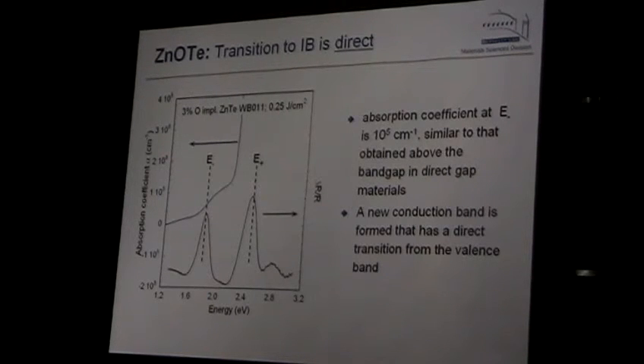So then we said, okay, now in order to make a solar cell, you need to have strong enough absorption. So we looked at the absorption coefficient of this, and in fact there is a strong absorption for this first transition, about at 1.7 or 1.8 electron volt. And the absorption coefficient is of the order of 10 to the 5 inverse centimeters. So it is decent absorption, it is very good. We cannot see the absorption to this state because there is a zinc telluride substrate, which blocks it, so we cannot see it. But this absorption, of course, is very strong as well.